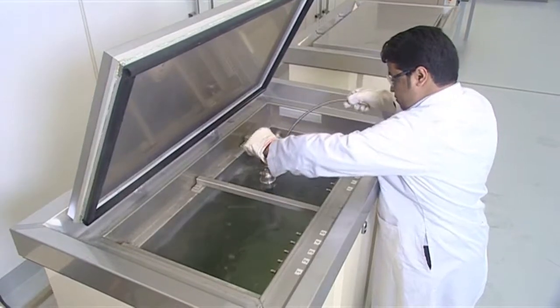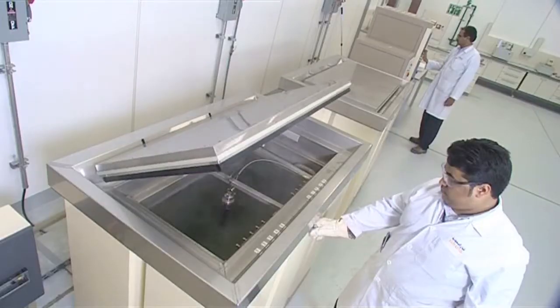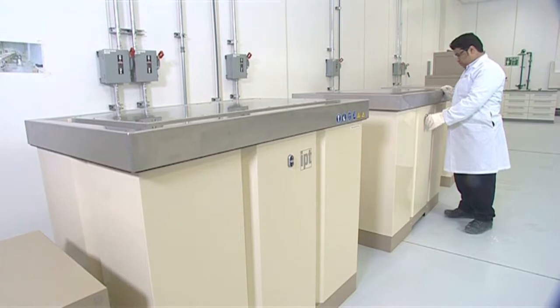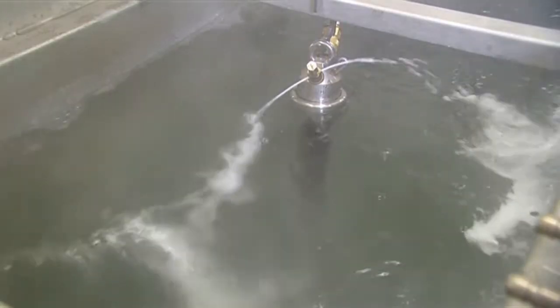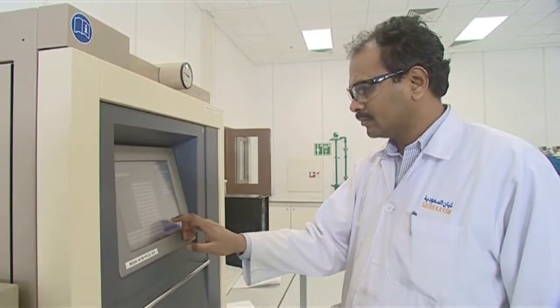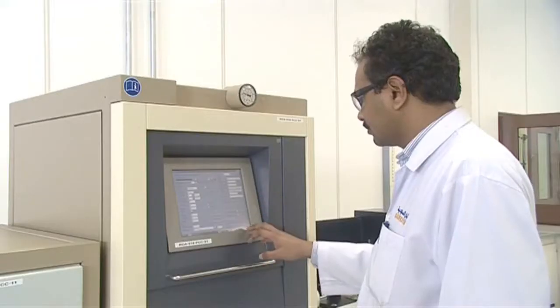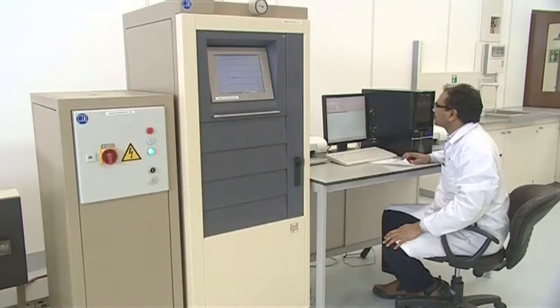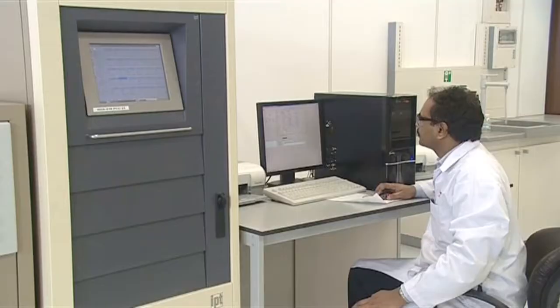Once the pipe specimens are ready, they are pressurized with water and kept in a water bath at 80 or 20 degrees centigrade. The duration to burst or rupture of the pipe is counted in hours. Hydropressure test is very critical for certifying and monitoring the quality of these grades.